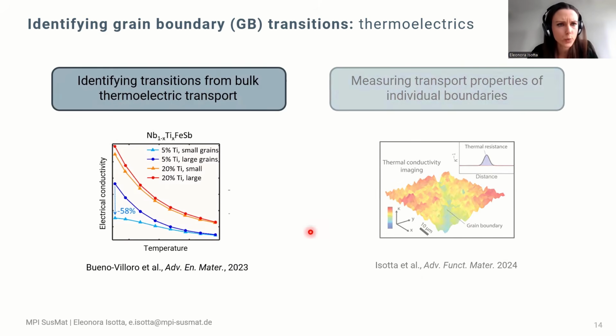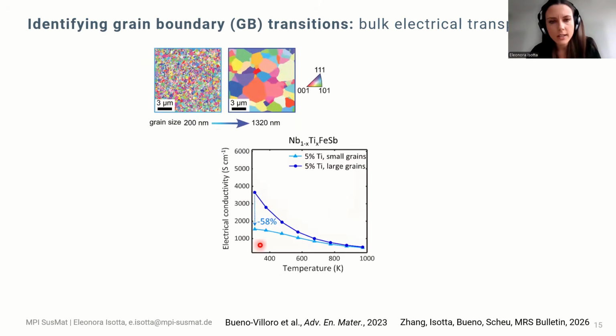So let's briefly start with the first one. This case was niobium iron antimony half-Heusler, where something pretty interesting was happening. In the 5% doped case, this niobium iron antimony was doped with titanium, and when 5% doping was introduced, a behavior was observed that was reconducible to electrical resistance at the grain boundary.